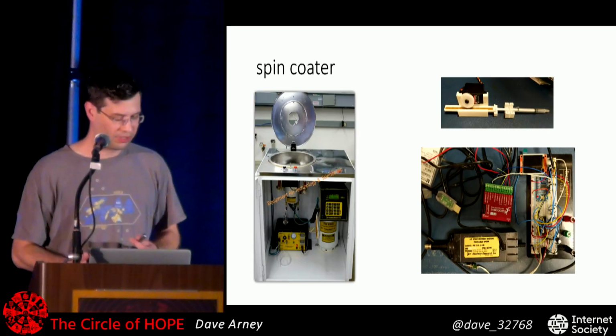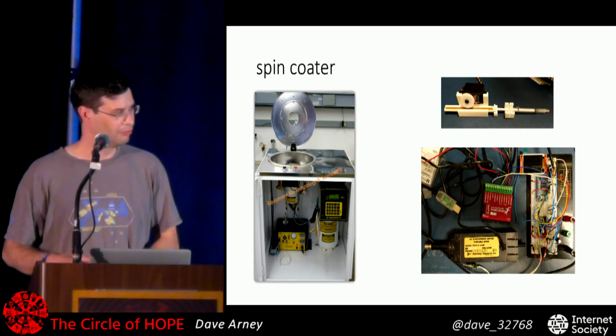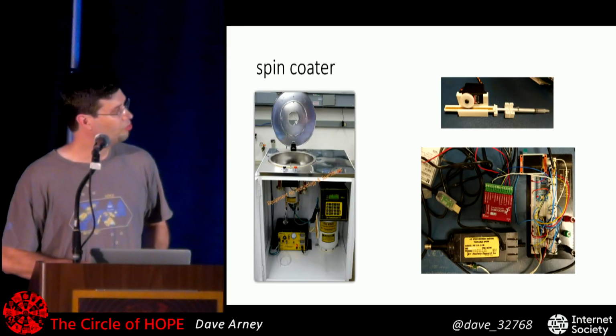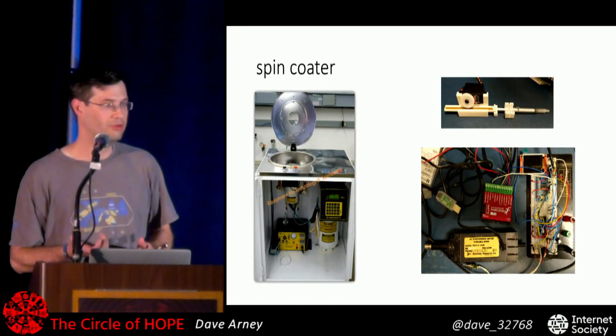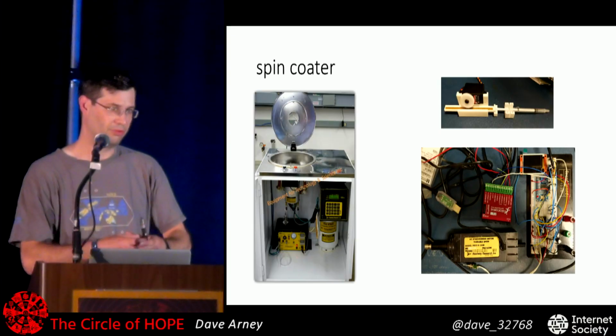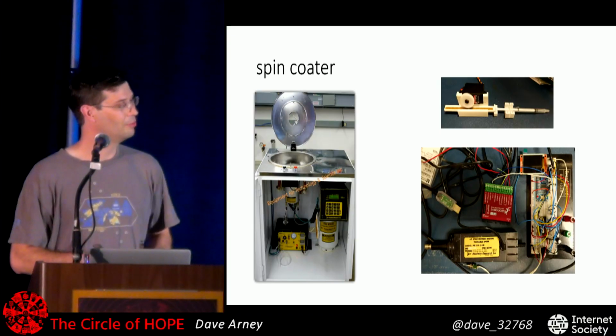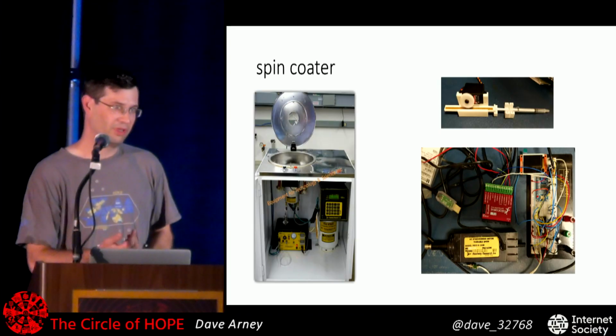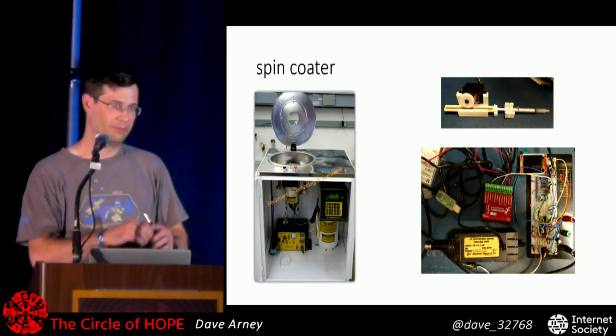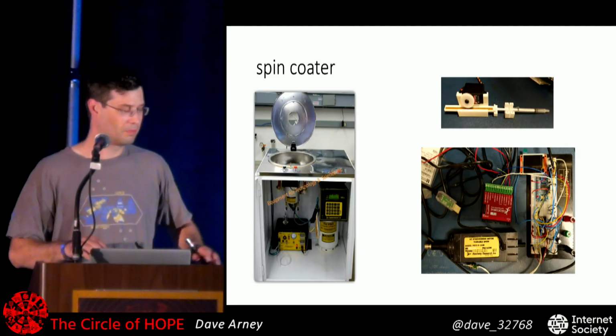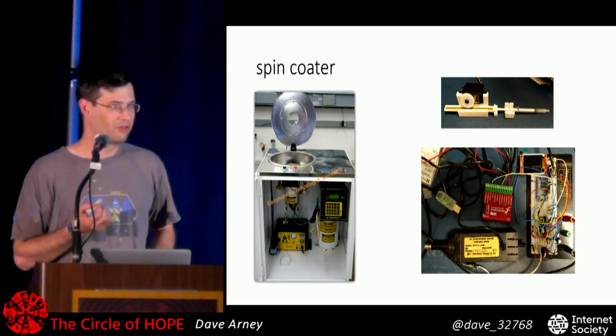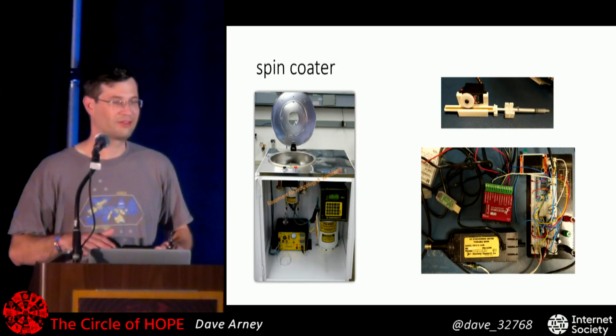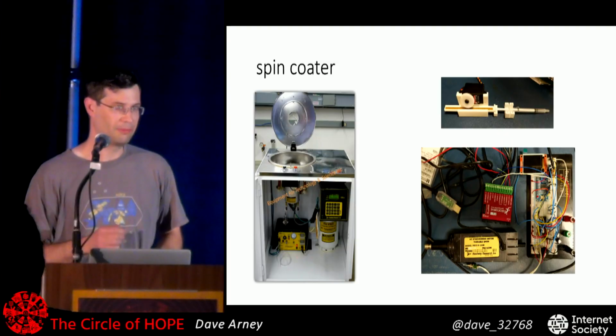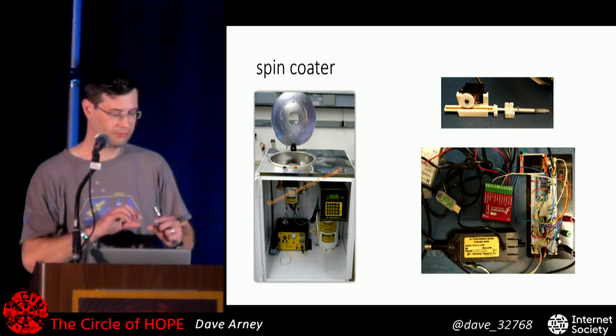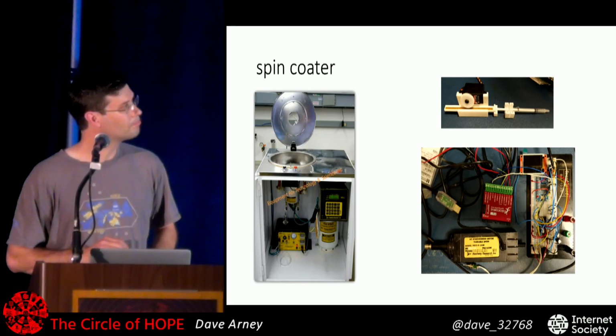And so a lot of what I've tried to do is sort of take and adaptively reuse that. So here's a commercial spin coater. What this does is, when you're using a liquid photoresist, you take your substrate, which is usually roughly circular with one flat edge. You spin it really fast. You drop a drop of liquid in the middle, and it just kind of flattens out. And by controlling the speed that you spin it, the acceleration and deceleration, and the amount of liquid you drop, you can control the thickness of the resist layer.